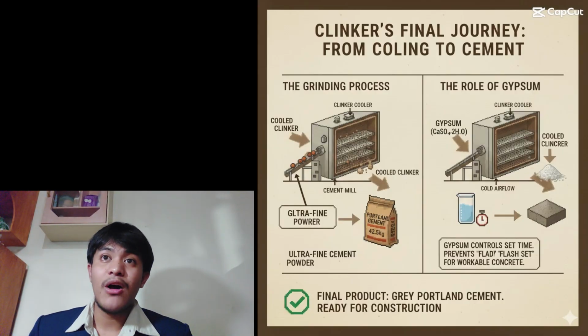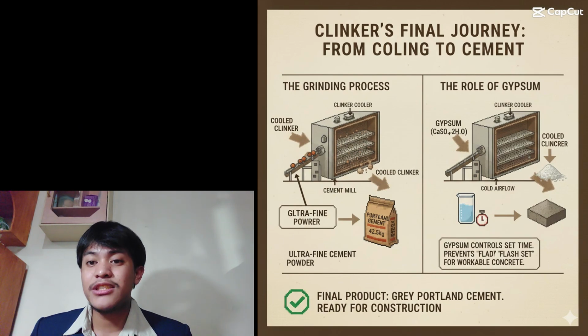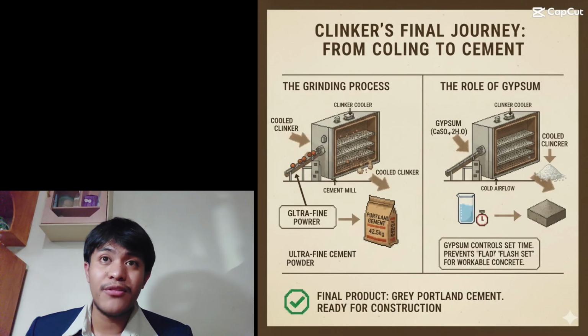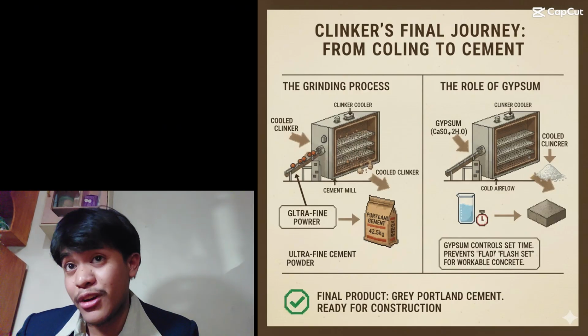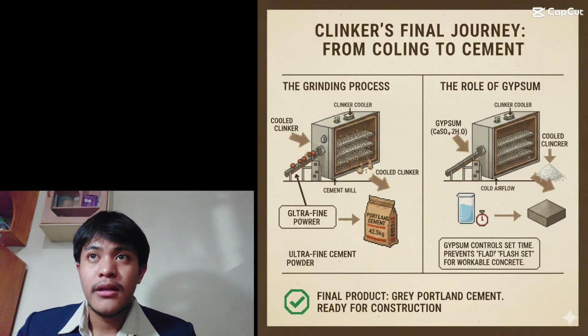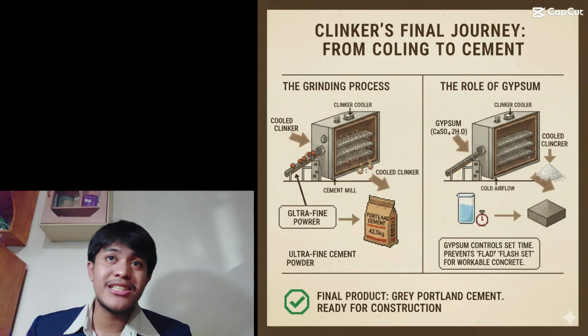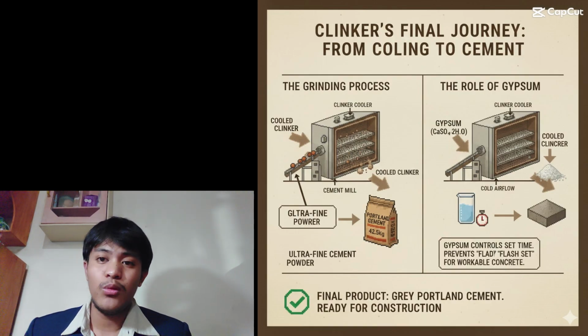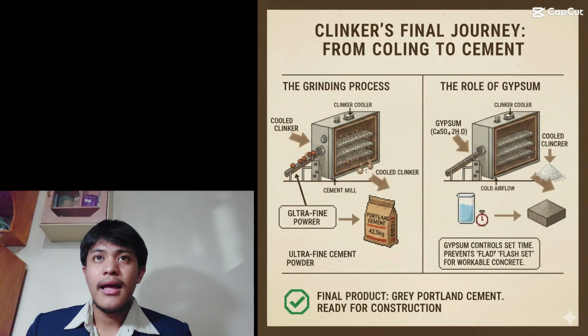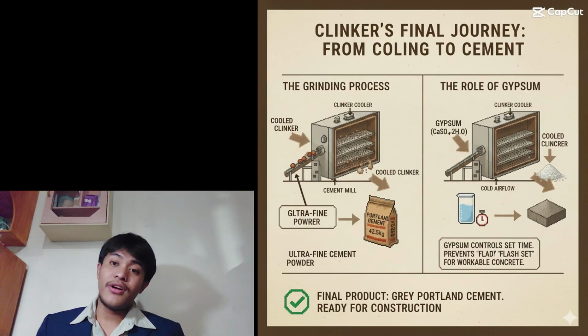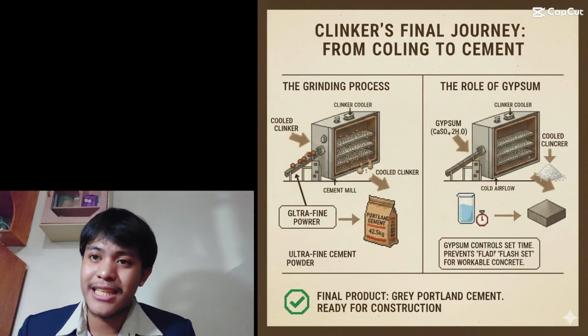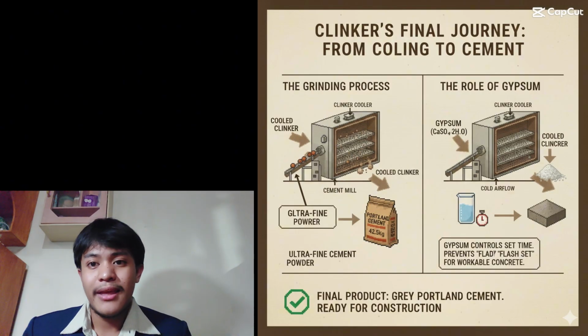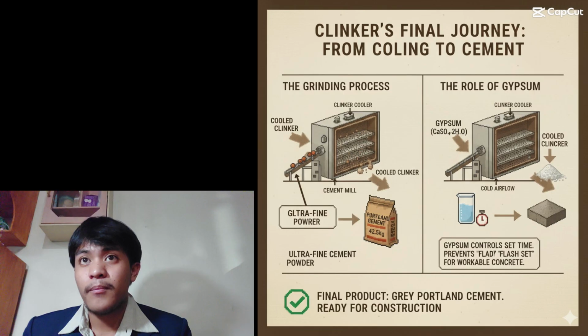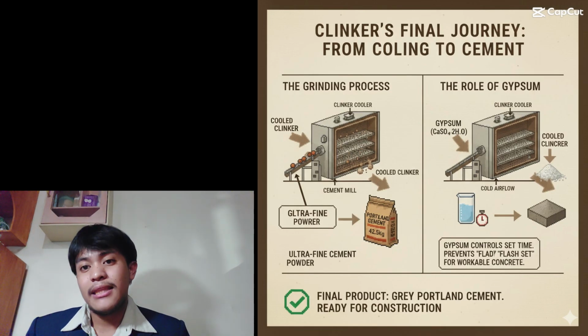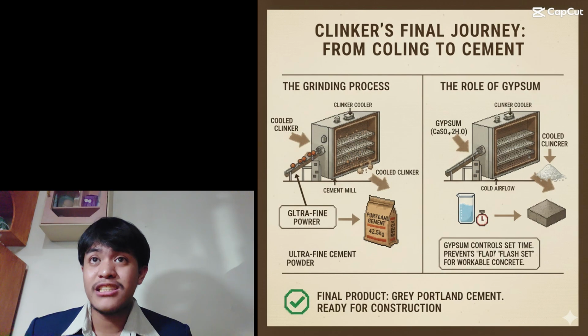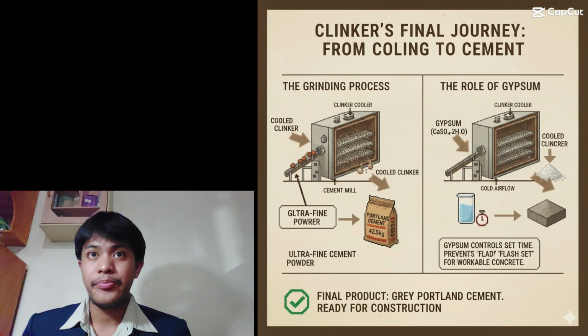Cooling also affects how minerals crystallize. Fast cooling leads to smaller, more reactive crystals, which hydrate better when cement is mixed with water. Slow cooling creates larger crystals that reduce reactivity and weaken performance. Alite, the mineral responsible for early strength in concrete, is especially sensitive. Without rapid cooling, it can decompose or form unwanted secondary compounds. The cooling process preserves alite in its strongest, most reactive form.